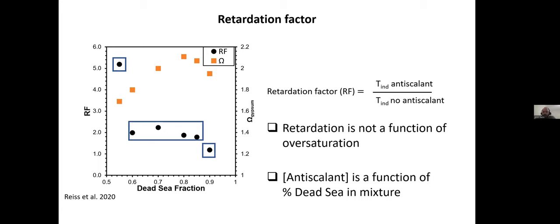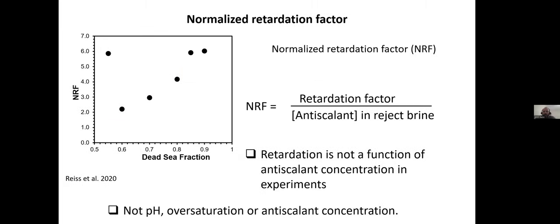Now, the concentration of the scale inhibitor, which is the last parameter, changes in each of the experiments because it comes from the fraction that's non-Dead Sea water. So the more of the Red Sea brine I add, the higher the concentration of scale inhibitor. So we could also normalize the retardation factor to the concentration of the scale inhibitor. I call this the normalized retardation factor. And when we looked at it, we see that the two experiments that have the most Dead Sea water, meaning the least scale inhibitor, and the experiment that has the least Dead Sea water, meaning the most scale inhibitor, have similar normalized retardation factors. So basically, the concentration of the inhibitor also does not allow me to predict the inhibition of gypsum precipitation in the Dead Sea Red Sea project.